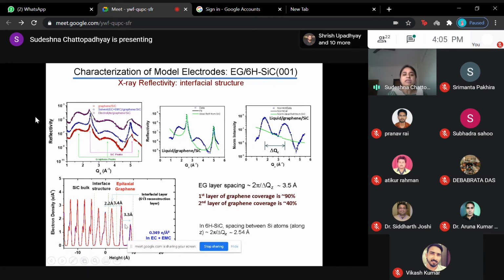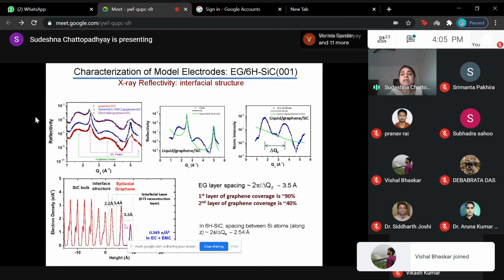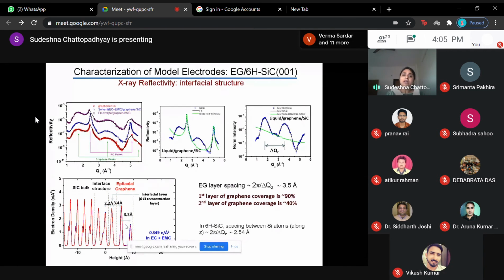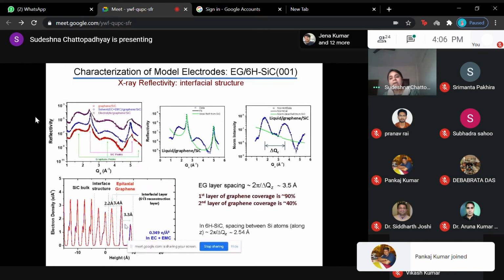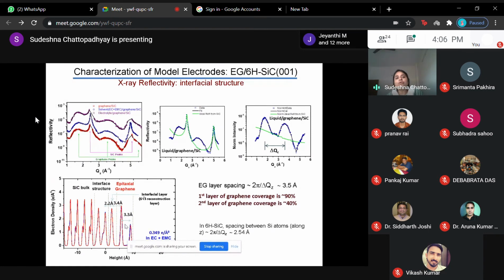So with the different media, we can even see the separation as well as the coverage of the graphene. Ideally we might think it is completely 100% coverage of graphene on silicon carbide, but what we can see is that the first layer of graphene coverage is 90% for a given system. Then there is the second layer of graphene coverage for the given growth parameters. Of course, if we know this information, we can tune the growth parameters to get what we want. If we want the second layer to also be 90%, then we will try to make it in that manner. We have to calibrate the growth parameters by taking many data sets like that.